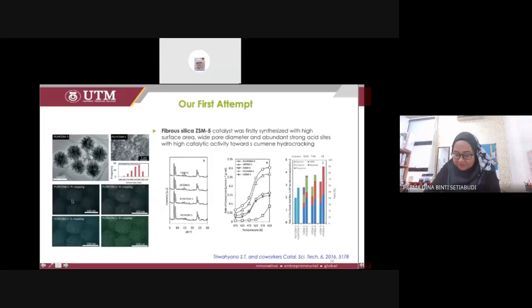As you can see here, the dispersion of the alumina is at the core of the fibrous silica, meaning that our synthesis is successful, to put the ZSM5 inside the core of the KCC1, the fibrous silica. Okay, so we try to apply it on the cumene hydrocracking.